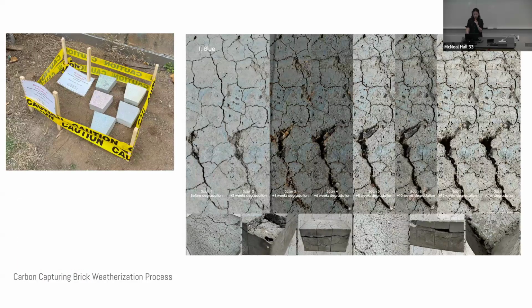So I tested out 5 bricks, and they're all tinted differently, so they're all composed of different ingredients. And I tested this over this past winter, through a 15-week winter time. All the samples went through winter weatherization, and the sequence you see here, from week 1, scan 1 to scan 8, is captured via GigaMacro imaging, and it tracks the exact same coordinate on the brick surface in 2-week intervals. So 2-week intervals, 8 scans, so that's approximately 15 weeks.